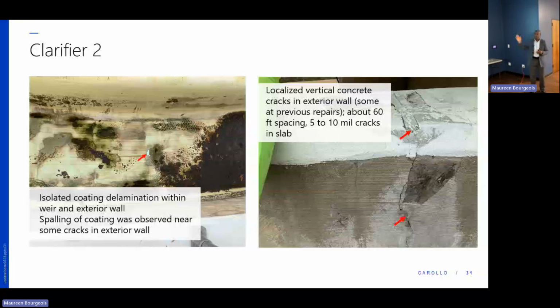And then for the areas, especially at the top where we saw that massive, aggressive erosion, we recommend the concrete repairs and the cracks for that, concrete repairs and application of a coating system. And we recommend that work to take place within the next 3 to 5 years.